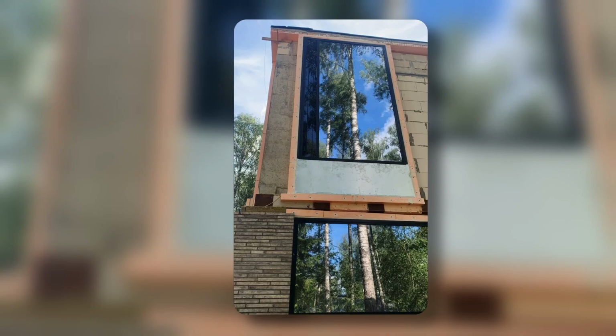I'll show a photo of what this structural vent sash looks like with the glass strip attached. It turned out amazing, but I ran into a lot of problems. First of all, sometimes the sealant seeps through this paint. You can actually see the lines of the applied sealant that the strip is glued with. They show through the paint. That's why we made the decision to repaint. We would make the glass strip, paint it, and then apply an additional protective lacquer coating on top so that the sealant wouldn't seep through or show. So you really need to paint all of this well.